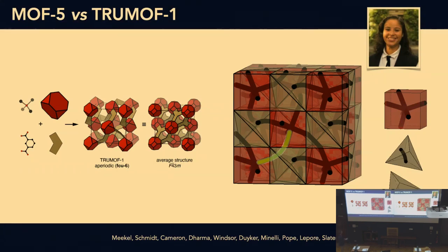Now, what's going on? Well, each one of these nodes, on a face-centered cubic lattice, each node site here has 12 neighbors at the same distance. But chemically, it can only be connected to 6. So it has to choose 6 of the 12. And when you do that on this lattice, you have to break the symmetry. There's no way of doing that and keeping the symmetry at the site. So when we do our Voronoi tessellation, the region of space associated with these clusters, when we draw in the connectivity, we have to show that symmetry breaking, the fact that you choose 6 out of the 12 edges, as it were, okay? There are, in fact, 24 equivalent ways of doing that for those who are interested.